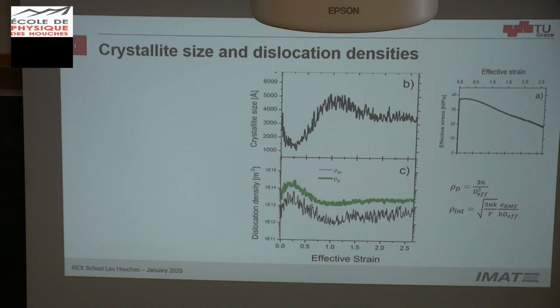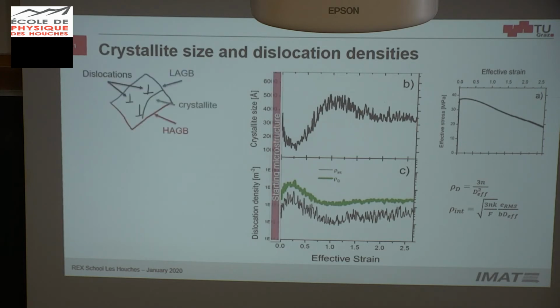At the beginning I was very disappointed, because the crystallite size is not the subgrain size, and it's not the grain size. It's its own entity, much smaller than the subgrain size, and it's only a coherent domain. It's very difficult to interpret and to correlate with the EBSD data. So how do we interpret this? We have the static microstructure that consists of low angle grain boundaries, high angle grain boundaries, and dislocations, and the coherent domain is the crystallite, which has a size defined by the previous processing.